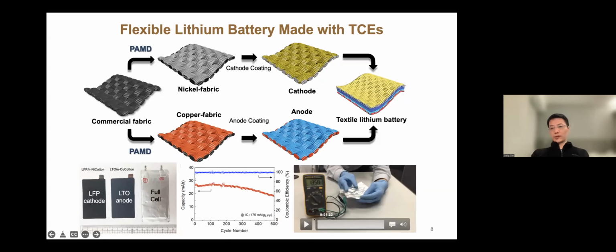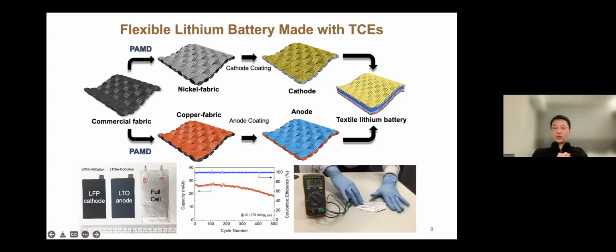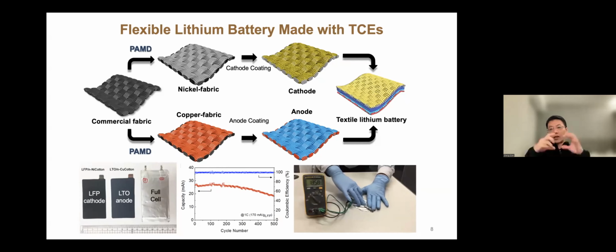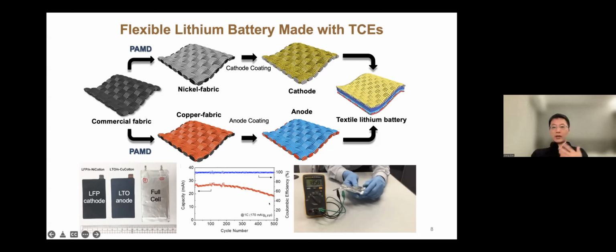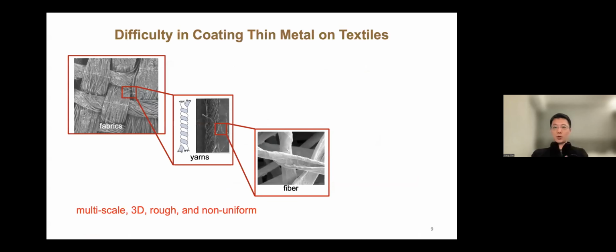You'll see in this video clip how flexible the cell is that we can produce, right? This is a cell at a size of roughly 5 centimeters by 3.5 centimeters, and this is a single electrode cell. You can simply fold it, or you can crumple it as you want, right? And this cell can safely cycle for about 500 cycles, as you see here. This was a cell that we produced a couple of years ago. Now, let me show you a little more detail about how we really make all this.